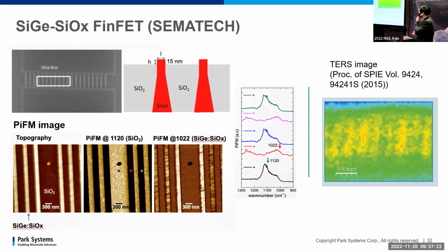Okay, and let's go to the silicon germanium and silicon oxide FinFET structure. This is silicon germanium and silicon oxide. One of the benefits of PIFM is that we can go through all the wavelengths to see what kind of material is in one spot. And when we know the structural wave number, we designate it, in this case 1120 for silicon oxide, and only the silicon oxide lights up. So we know that the light area is the silicon oxide. And when we run the wave number of 1022 for silicon germanium, we know that this area has the silicon germanium.